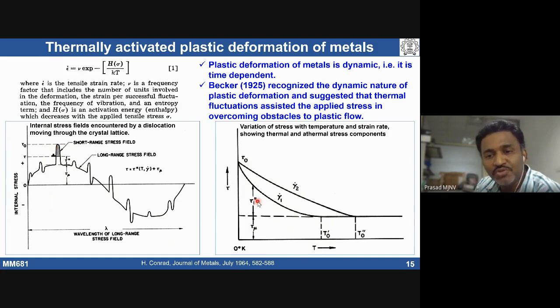The moment you apply some temperature, thermal fluctuations can assist the applied stress. That means the stress required to overcome thermal barriers is going to come down. Depending on temperature, your stress requirement is going to come down, because thermal fluctuation is also assisting. Some of the barriers can be overcome by just giving a temperature.